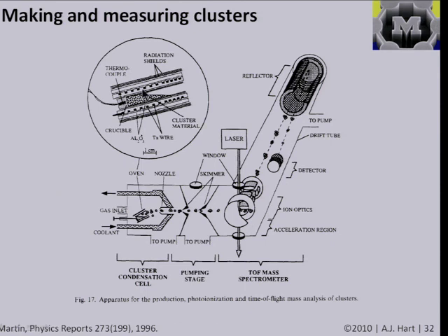So your titanium nitride, say, powder, could be sitting in a little container, and at very low pressure, if you can vaporize it and then basically drive it down a column where you know the relationship between the time that different clusters or different sizes will take to fly to a certain destination, because their speed is going to depend on their size. You can electrically detect the arrival of clusters of certain sizes, and you can create that spectrum that you see there.